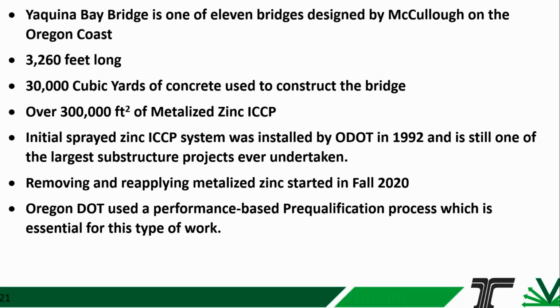So the next bridge that was done, the first big bridge that was done as part of this program, was the Yaquina Bay Bridge. It's one of 11 bridges that were designed by McCullough along the Oregon coast. It's a little over 3,000 feet long, has over 30,000 cubic yards of concrete in it, and a little over 300,000 square feet of metallized zinc impressed current cathodic protection was applied in 1992. At the time, it was, I think, the largest substructure project ever undertaken. And even today, it's certainly one of the top 5 or 10. Over the years, we'll see how it served a useful life, but it was removed and reapplied in 2020. And Oregon DOT learned a lot over all these years, and one of the things that they learned is that they used performance-based pre-qualification, which is really helpful for quality control.